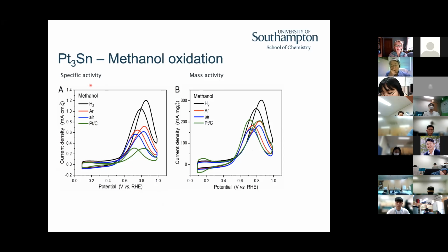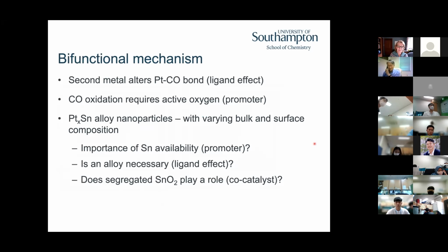Those of us in academic science are very interested in this and trying to develop structure activity relationships. We are very interested in specific activity. The companies we work with are really only interested in mass activity, right? So this is how much current I'm going to get for every gram of platinum I have, right? And you can see that the effects are a little bit less when we start to consider that. So how is that CO activating?